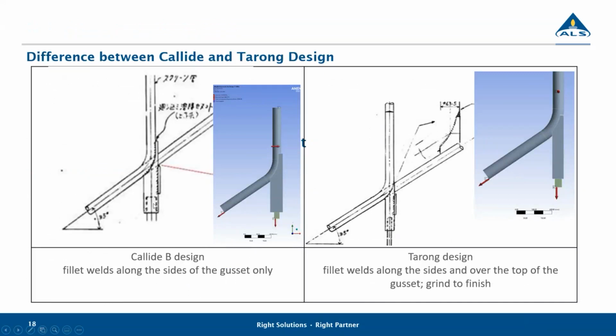You can see Callide, the bracket runs up quite high. It's got a very abrupt stop at the top, and the welds are just on the side. So the load transfers through this bracket into the tube, and if you can visualize some flow, it needs to flow into the tube. So what we're seeing is that that tip of the bracket is actually not working at all. So the stress flows into the bracket, but where it runs through that corner is where the stress is concentrating.